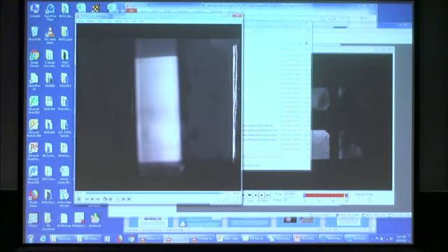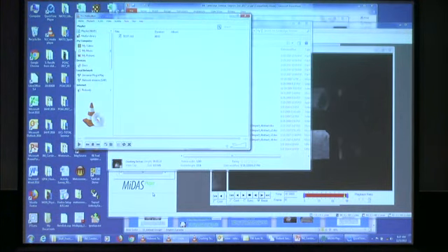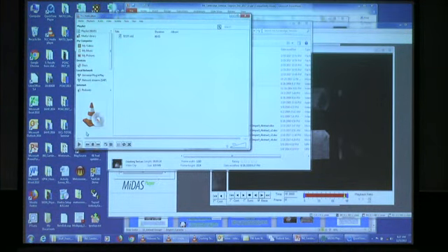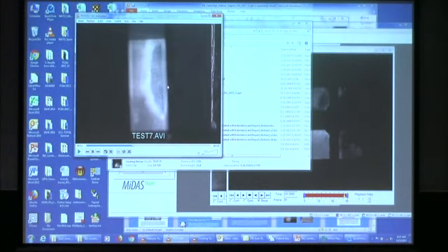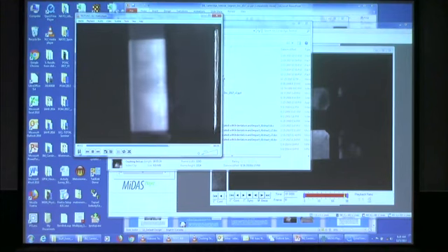So we're looking down through the platen at the hard zone ice that I was just referring to, we're looking down through it now, whereas before we were looking sideways. So this is intact ice. Spallation is happening from the back side, and where that ice is in contact with the platen, you have the slurry being produced and quickly being ejected.